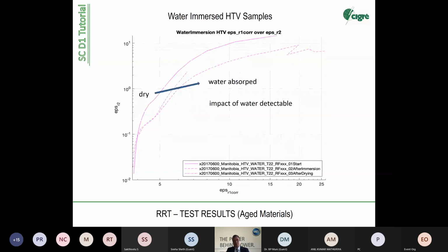Here it's a HTV sample. Keep in mind, mineral filled, alumina trihydroxide, 50% by weight. So we see a clear tendency here from the dry response to the water absorbed response, and you can say it's clearly the impact of water is detectable.